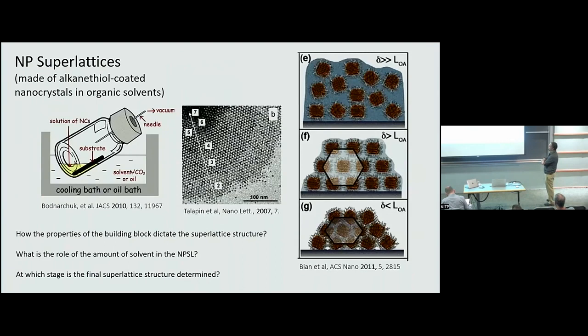So today I'm going to focus on a very specific type of nanoparticle superlattices, those made of inorganic nanocrystals coated with alkanethiol ligands. There are of course many other types, like superlattices made with DNA ligands, but today my talk is going to be about this special type of systems. The idea here is that you can do self-assembly just by taking a solution or a suspension of these nanoparticles in an organic solvent, which is a good solvent for the ligands, and then you let it evaporate, and at some stage in the evaporation process, there will be the formation of some long-range order structure, okay? And then, of course, you remove the remaining solvent and get to the dry superlattices.